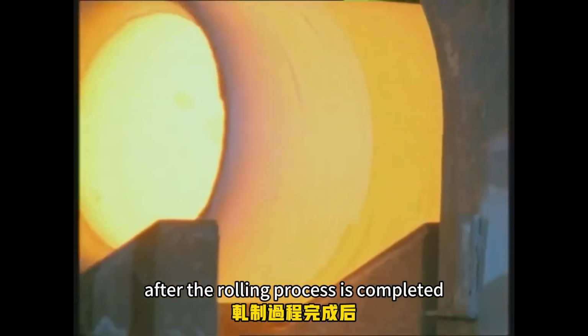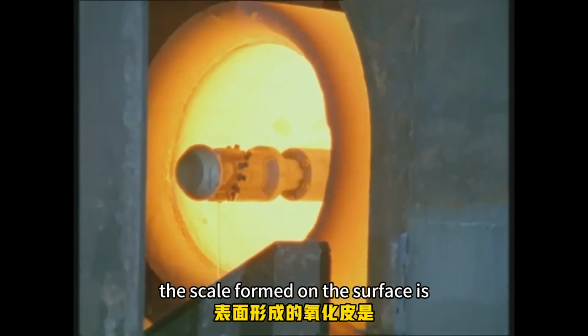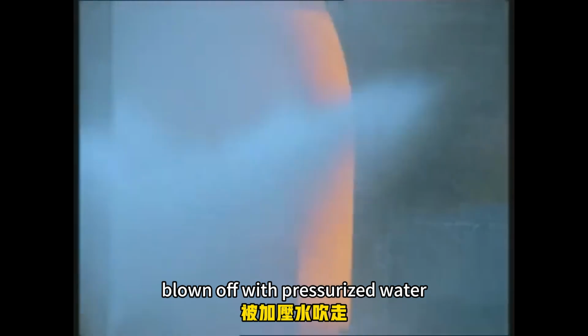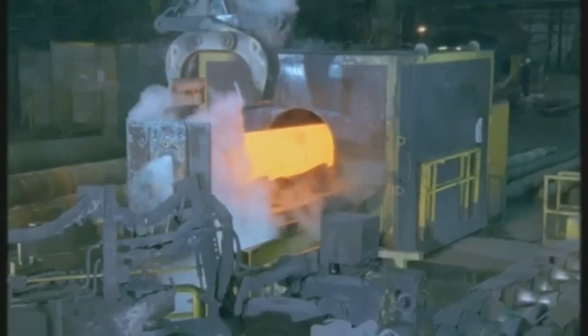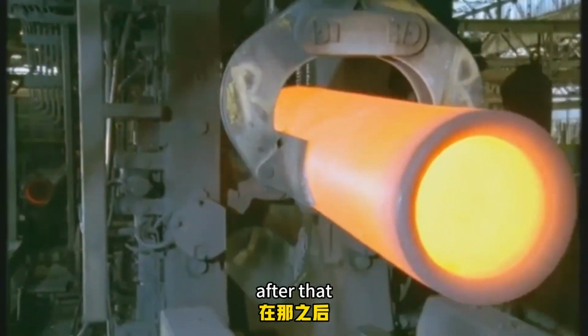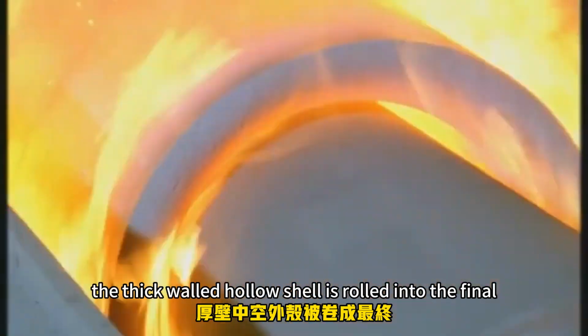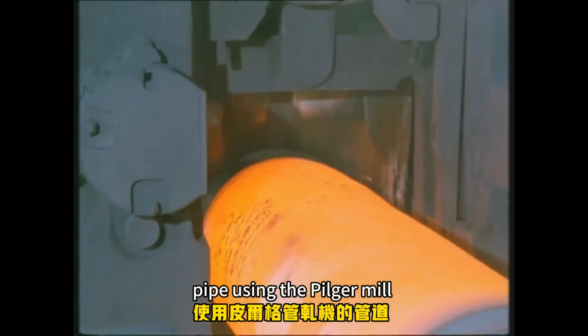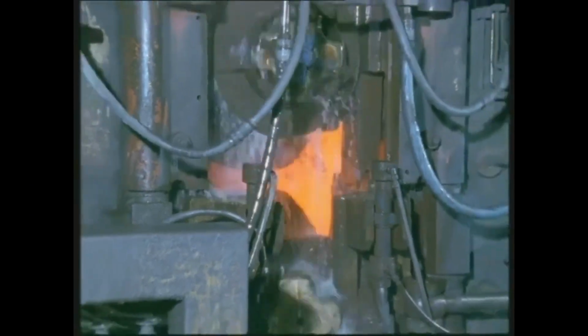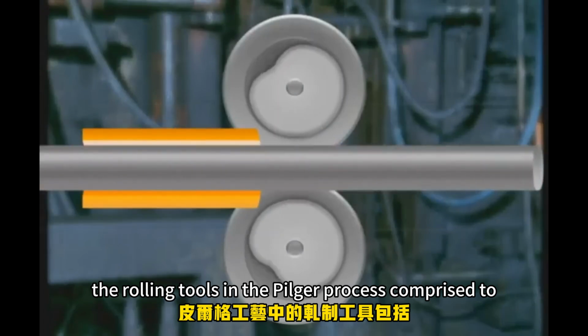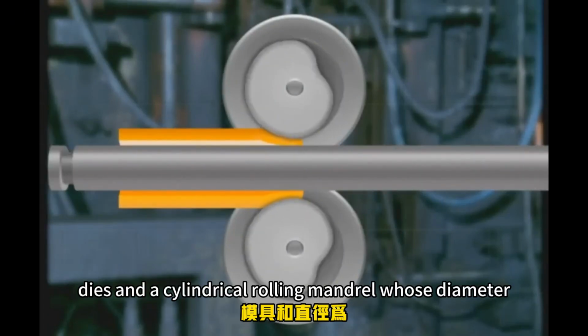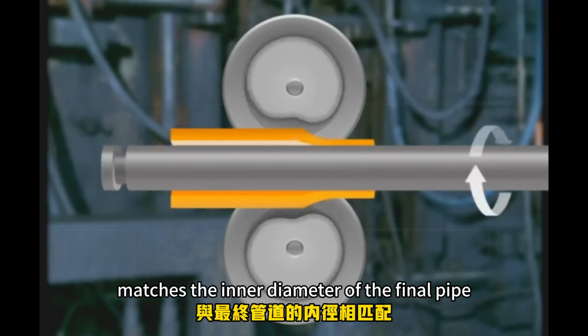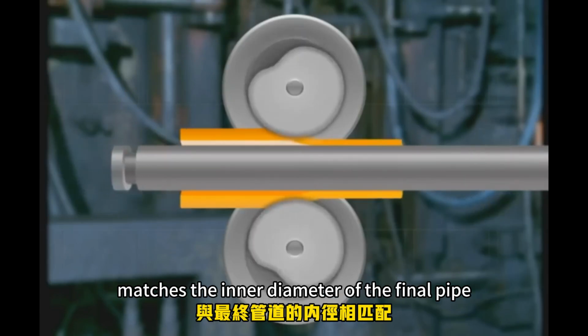After the rolling process is completed, the scale formed on the surface is blown off with pressurized water. After that, the thick-walled hollow shell is rolled into the final pipe using the pilger mill. The rolling tools in the pilger process comprise 2 ring dies and a cylindrical rolling mandrel whose diameter matches the inner diameter of the final pipe.